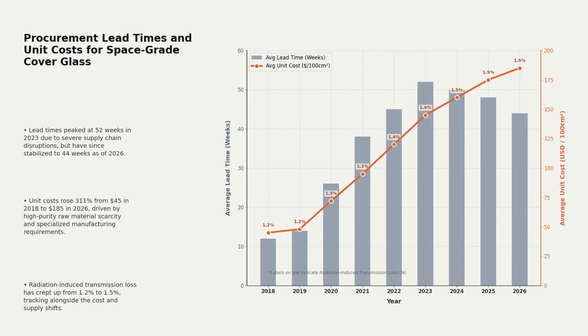Simultaneously, unit costs for standard 100 square centimeter cover glass escalated by 311%, rising from $45 to $185. This price surge reflects both raw material costs and the high-yield manufacturing premiums charged by specialized producers. Despite these rising costs, substitution is not a viable engineering option. Non-doped alternatives suffer from rapid radiation browning, which degrades light transmission. Cerium-doped glass limits simulated 10-year transmission loss to under 1.5%, making it mathematically indispensable for orbital longevity.